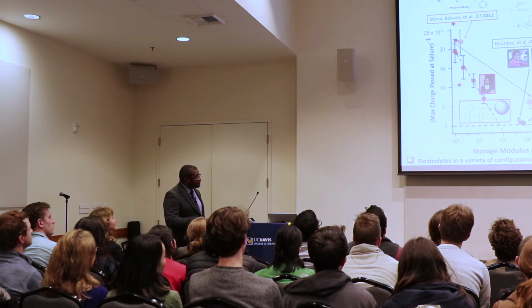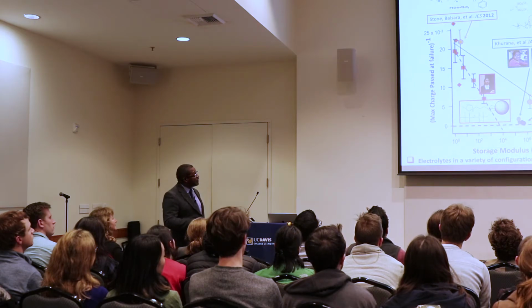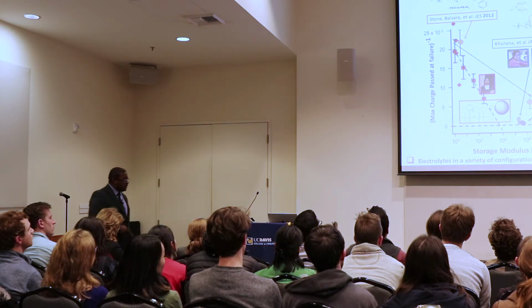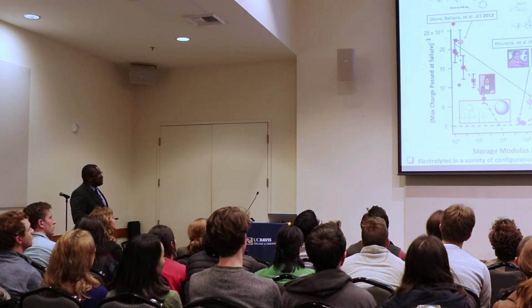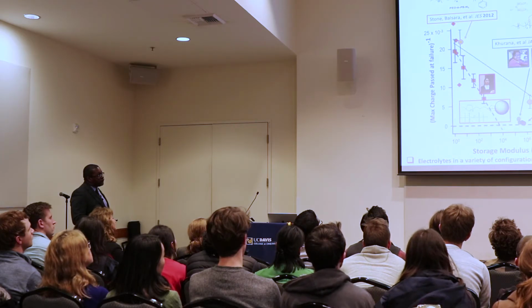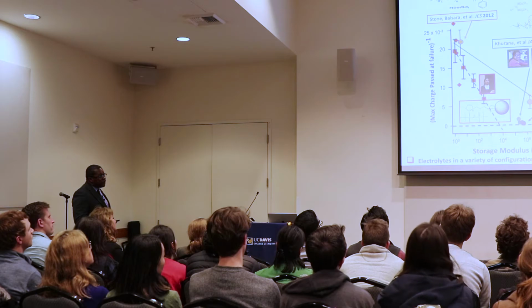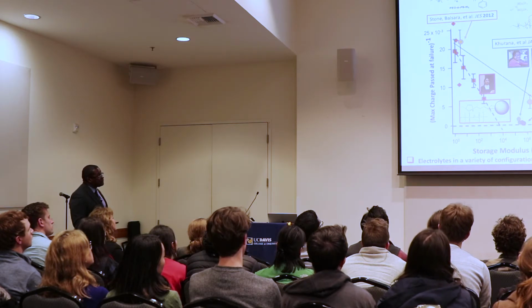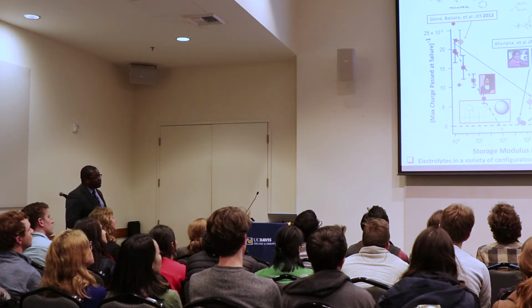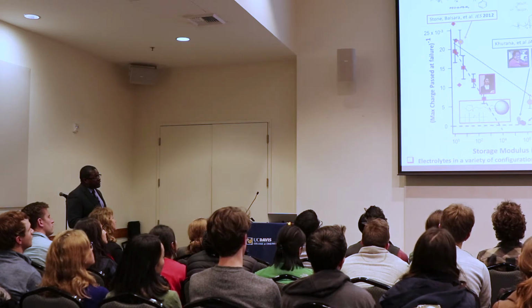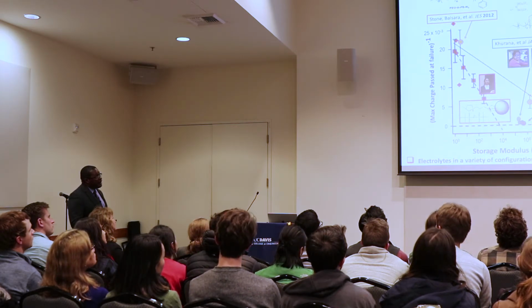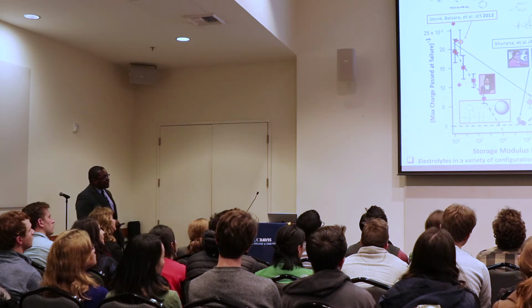And I'm plotting it against the modulus of the material, for different systems. For polymers, you can see we're close to 0 for moduli a little bit below what's normal for an entangled polymer. For hairy nanoparticles, it's good. For the anodized alumina, you've already seen that. And for the crosslinked nanoparticles, it's here.